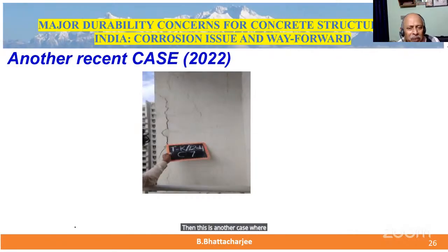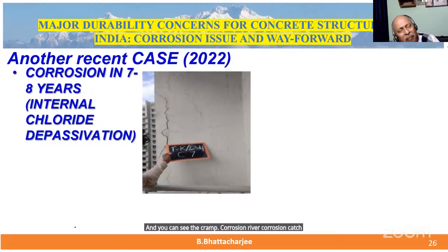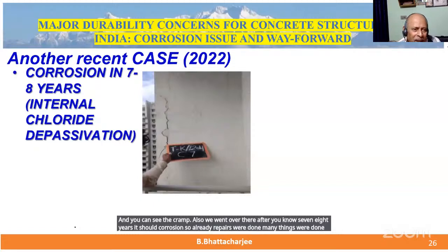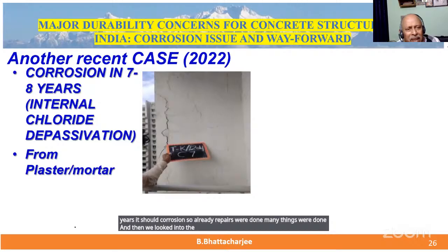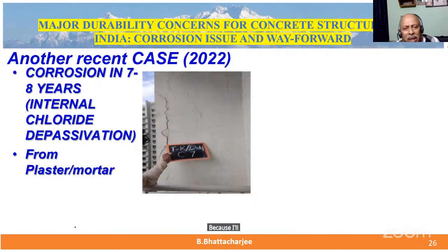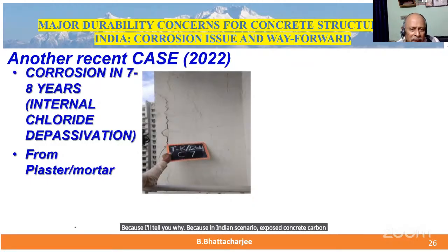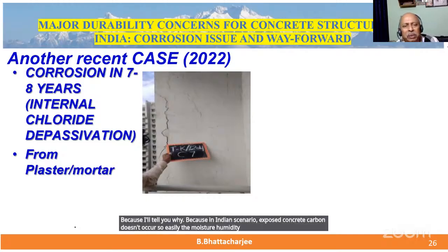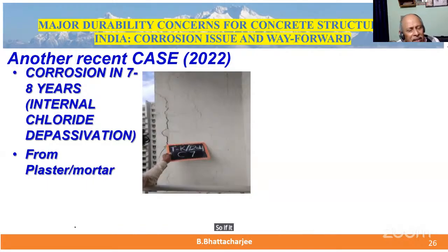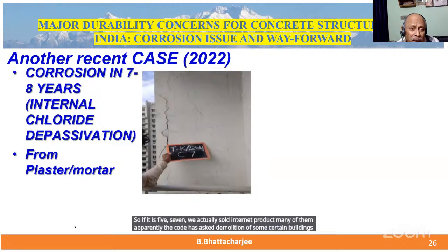Then this is another case where 2022, and you can see the crack, corrosion, rebar corrosion cracks. There also we went after 7, 8 years it showed corrosion. So already repairs were done, many things were done. And then we looked into the chloride, and in 7, 8 years, carbonation would take much longer time. Because I'll tell you why. Because in Indian scenario, exposed concrete, carbonation doesn't occur so easily. The moisture, humidity condition required is 50 to 70%, or maybe 55 to 65%. So if it is 5, 7 say, internal chloride, many of them apparently the court has asked demolition of some certain buildings with high chloride.